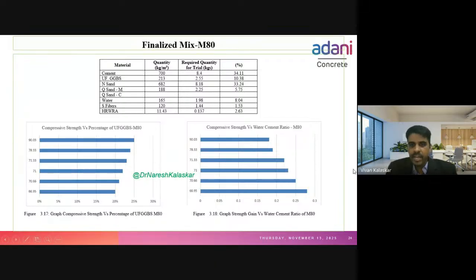This is M80, and you can see the water cement ratio here. When you are increasing the water cement ratio to 0.28, you got strength of 66.95. When you are reducing the water cement ratio, like for M80, we have used 0.18 water cement ratio, you got 90 MPa strength. So in this graph, I want to say that when you are increasing ultrafine GGBS, you are getting more strength. When you are reducing the water cement ratio, you are getting more strength. So these are the very important factors which you have to keep in mind while designing the UHPC.